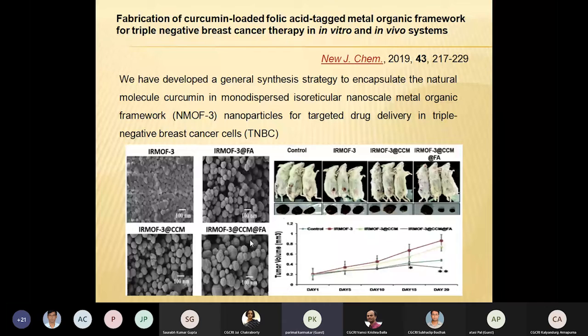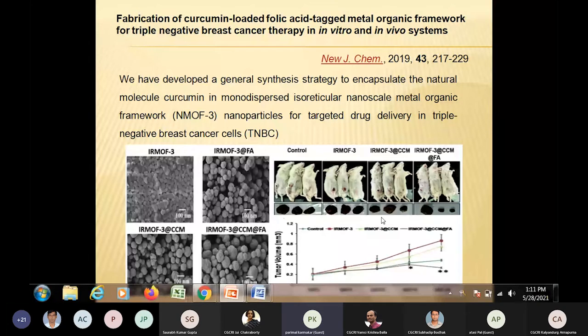And then for in vivo studies, we use the BALB/c mice, where we inject the cell line 4T1, which has the capability of producing cancer in the BALB/c mice. And then we treat them with these different components at 3 days interval, until 3 or 4 doses. And then after day 20, we sacrifice the mice and measure the volume and weight of the tumor. As you can see nicely, the targeted delivery of curcumin can reduce the tumor, whereas folic acid alone has nothing to do with the cancer, but the targeted curcumin can do so to some extent, but folic acid conjugated curcumin with this metal organic framework can regress the tumor.